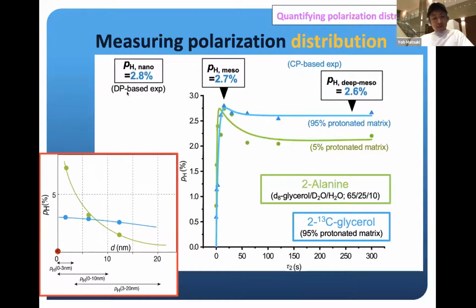Now, what if we do the same thing on highly protonated sample? We did that, we found this very much flat polarization distribution, which is not surprising, right? Because this very strong spin diffusion supported by dense proton network is really pulling out the polarization farther away in space from the electrons, leading to this flatter polarization distribution. Maybe people kind of knew this is happening in mind, but this is experimental. We are able to directly measure the polarization distribution in space.